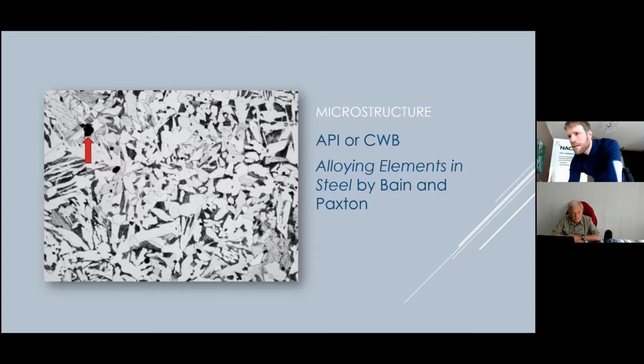So microstructure is determined by our chemical composition, our heat treatment, our forming, and also in service with temperature and time we got up to. And microstructure determines our mechanical properties and our corrosion resistance. So it's very important. A decent metallurgist can look at a microstructure and determine whether something is fit for service or determine the damage mechanisms.